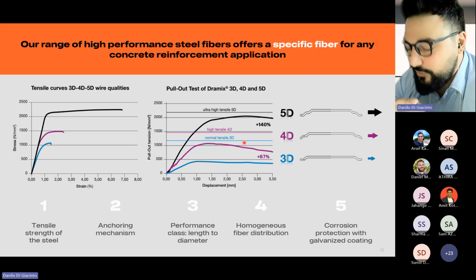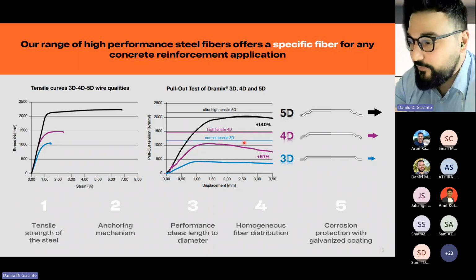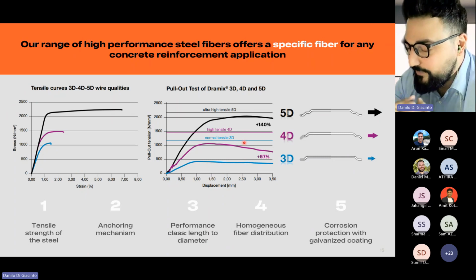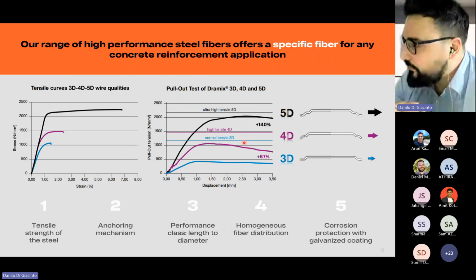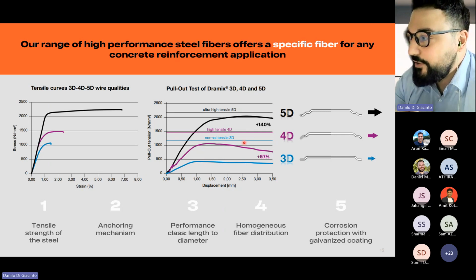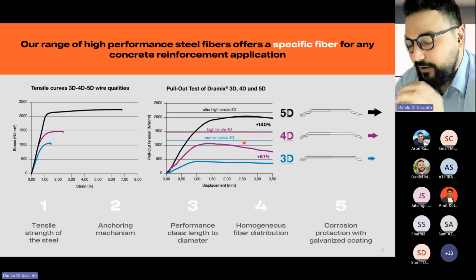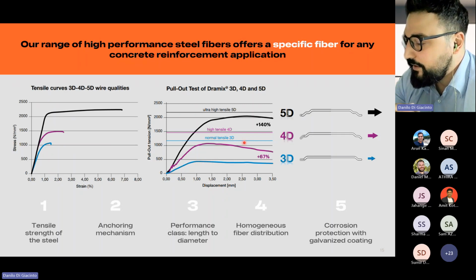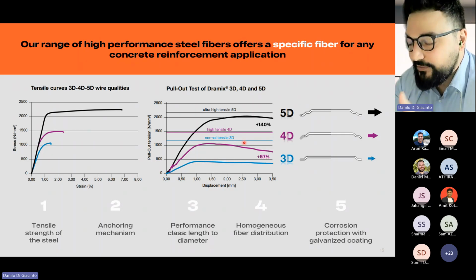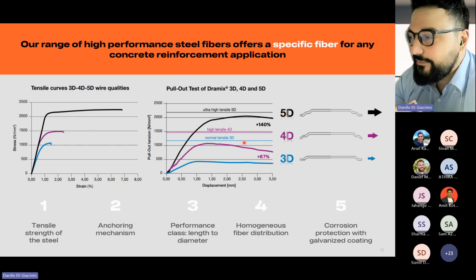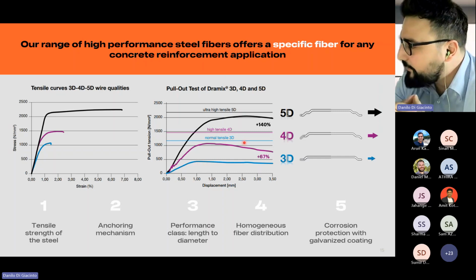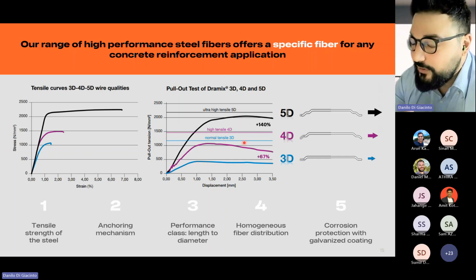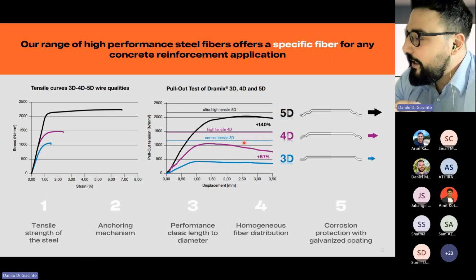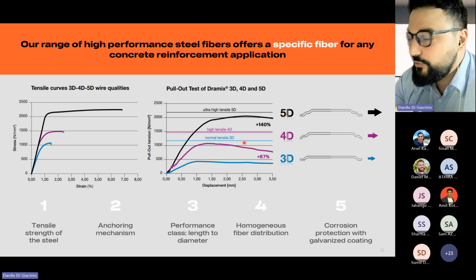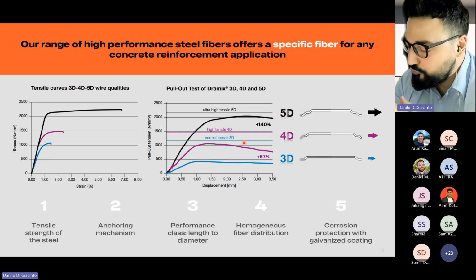So the 5 main points for the Dramix fibers are actually the tensile strength of the steel, which can be very different according to the fiber type, and the anchoring mechanism, so the type of anchors at the end of your fiber, which can lead to different mechanisms. The performance class of the fiber itself depends on the length of the fiber and on the diameter of the wire. Then the fact that it's a homogeneous reinforcement, and thanks to the zinc coating, we can have corrosion protection.